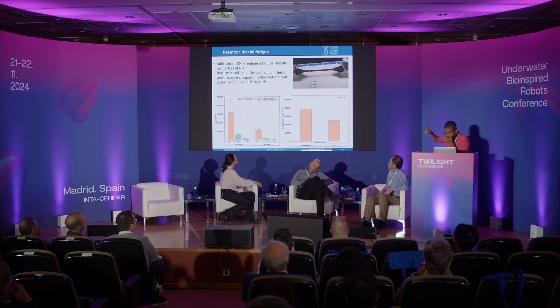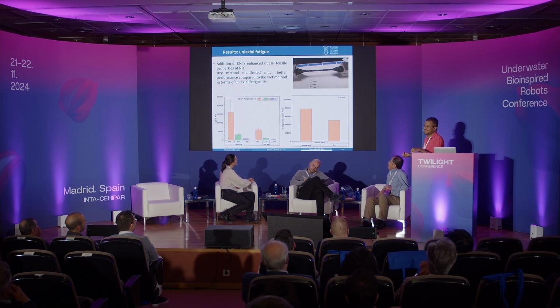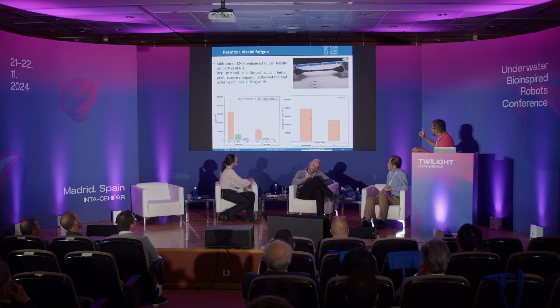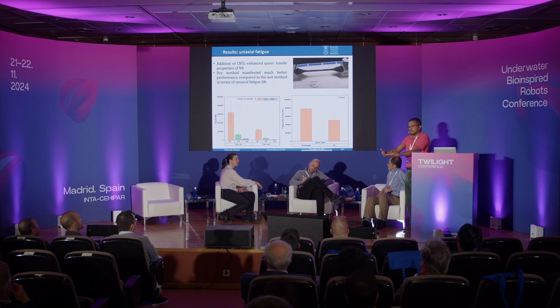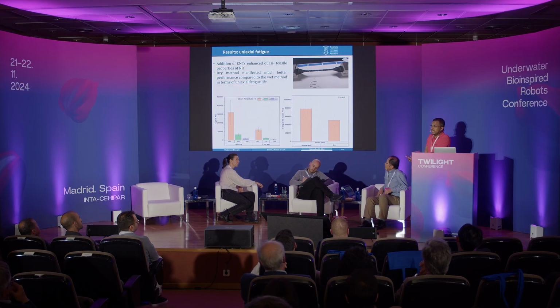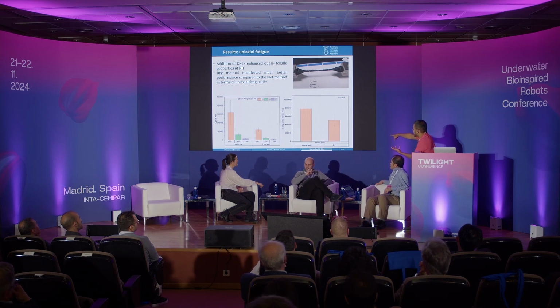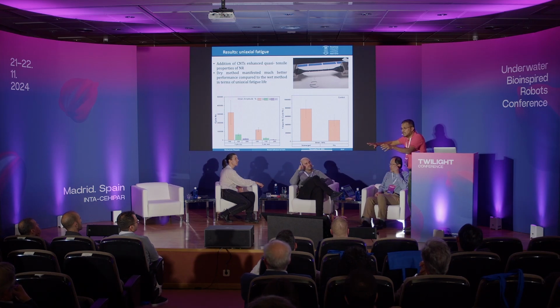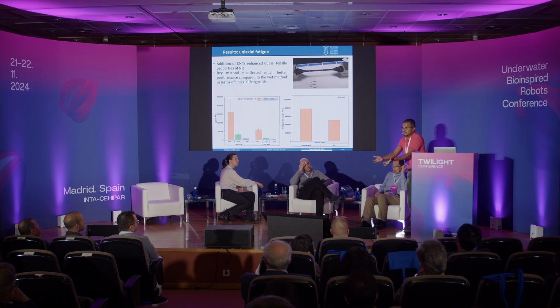Okay? So we found that for CNT-filled elastomer, the fatigue life is significantly less if you take the virgin sample. So here you can see, we did 2 types of fatigue test. One is submerged. We put the sample under water, and we did this fatigue test with the virgin sample. That means it took 6 months to get 1 set of data, right? Sometimes 3 months, sometimes 6 months. And for the dry case, I'm pulling it up to 100% in dry condition, no water, and I'm putting this sample up to 100% in wet environment, that means with water, right?